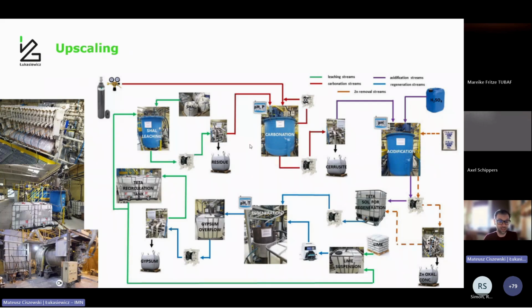As you can see, there are four main reactors. It was done in our premises at IMN, the Institute of Non-Ferrous Metals. There is the leaching reactor for the leaching, the carbonation reactor for purging CO2, the biggest one at 3.5 cubic meters, and acidification, just to add concentrated sulfuric acid to dissolve and evolve carbon dioxide. And the last one, the fourth reactor, heated by a heating mantle, is for the regeneration, for production of gypsum and to regenerate TETA so it can be recycled to the beginning of the process. Of course, IBC containers for any buffer solutions were there.